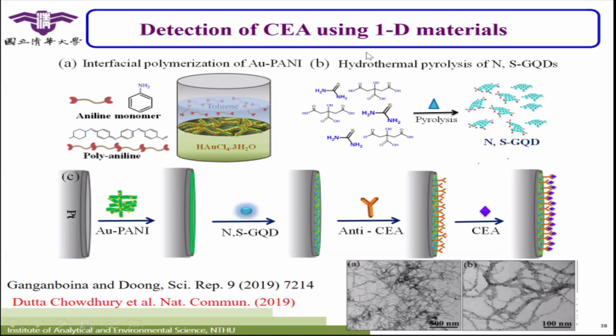We tried to immobilize the N,S-GQD on the polyaniline. Polyaniline is one kind of conductive polymer. We used aniline as the monomer and fabricated it into polyaniline. We put gold on the surface, so you can see the gold here, and then put the NSGQD here. So we immobilize these materials on the surface of the electrode, platinum, and some others.